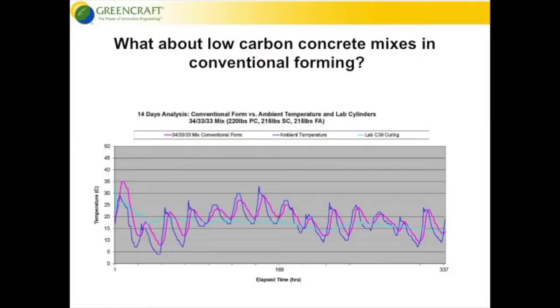So we did a number of different concrete mixes, as I told you. This mix here is a very low carbon concrete mix: 220 pounds of Portland cement, 215 pounds of slag cement, 215 pounds of F fly ash. In a conventional form, you can see there's not a lot of heat, not a lot of energy in it. In the same environment, you get about 35 degrees Celsius in that mix. And then, again, you drop the same way. By next morning, you follow the same ambient up and down pattern.